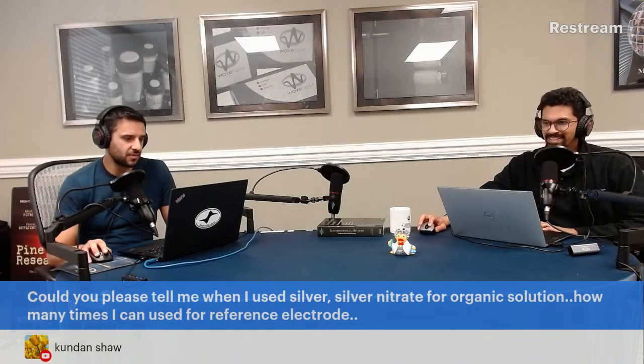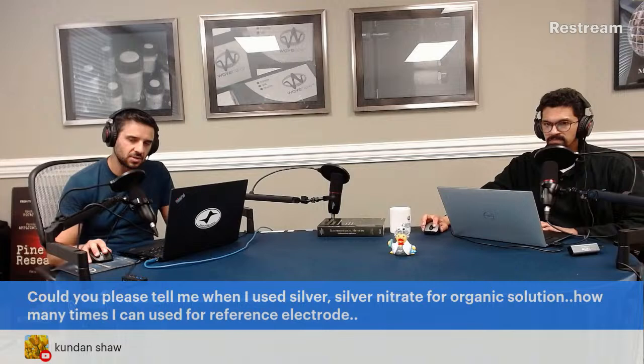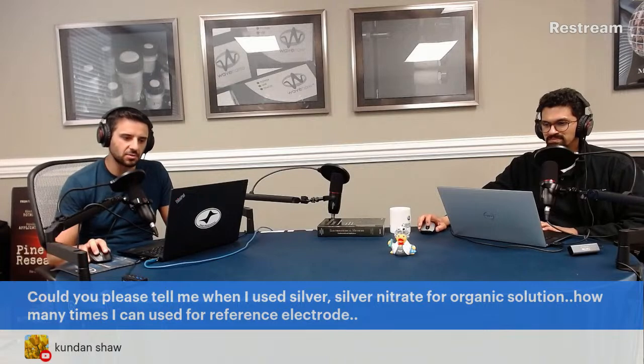Frankly, right? If it's moving around, your peak shows up at 400 millivolts. Who's to say on the next scan it shows up at 500 or 300? Is that chemistry, right? Did your electrode get better between cycles 3 and 4, or is your reference electrode just moving around? It's hard to know the answer to that question, so you have to do some independent verification of your reference electrode, or use an internal standard, like we said.